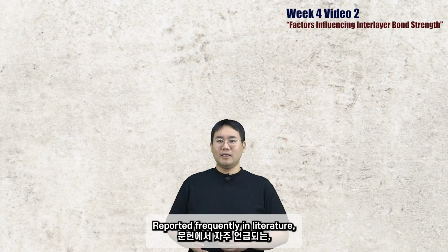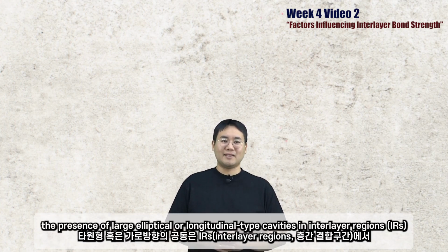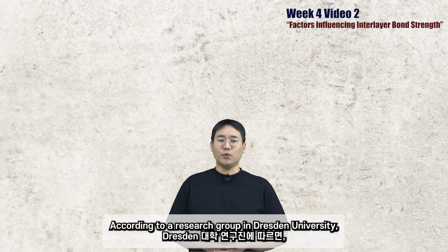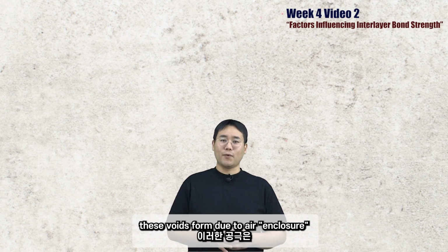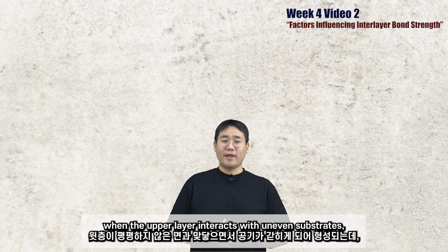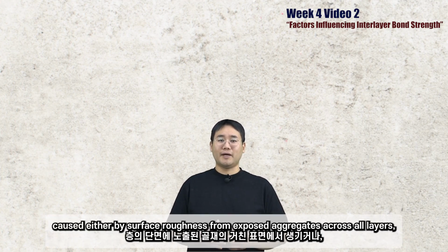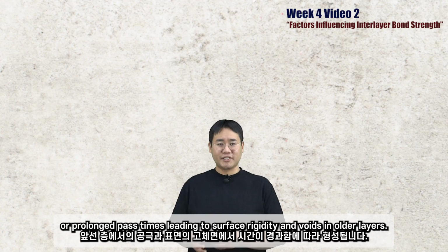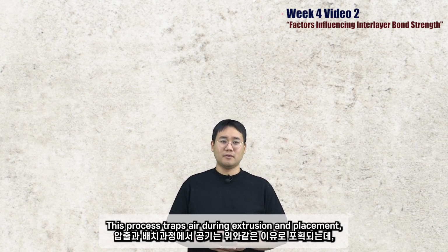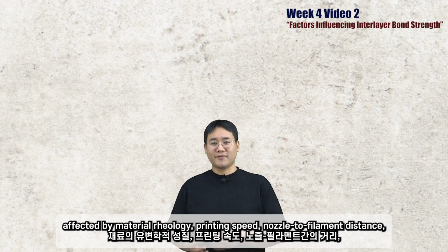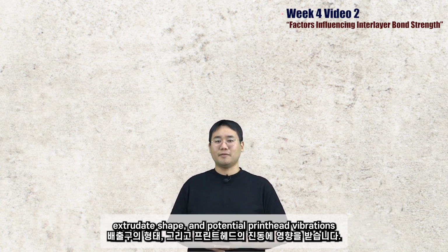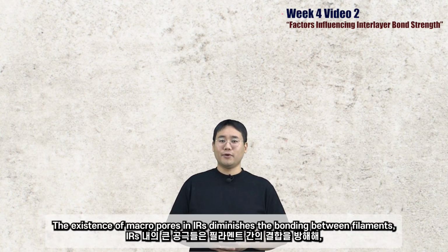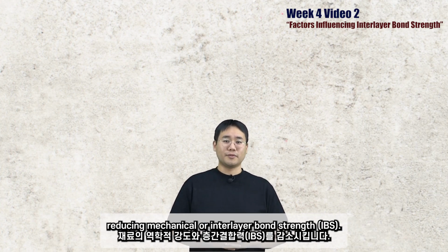Reported frequently in literature, the presence of large elliptical or longitudinal type cavities in the layer regions is a notable observation. According to a research group at Dresden University, these voids form due to air enclosure. When the upper layer interacts with an uneven substrate, caused either by surface roughness from exposed aggregates across all layers or prolonged pause time leading to surface rigidity, voids form in the layers. This process traps air during extrusion and placement, affected by material rheology, printing speed, nozzle to filament distance, extrude shape, and potential print head vibration. The existence of macro pores in the interlayer region diminishes the bonding between the filaments, reducing mechanical or interlayer bond strength.